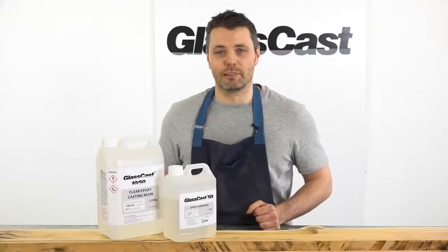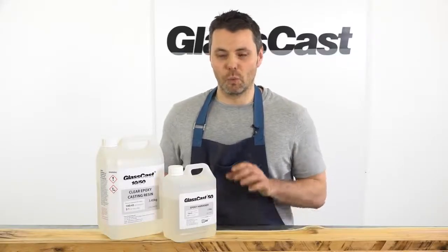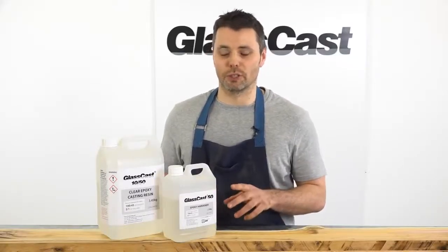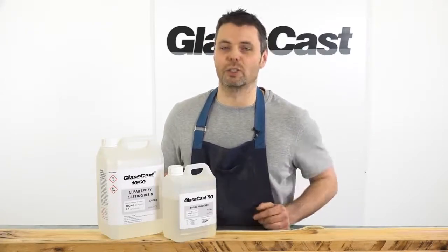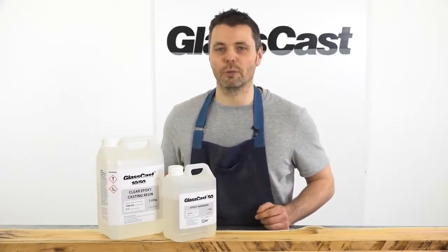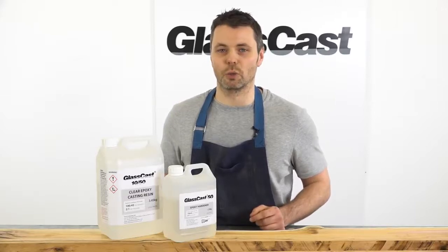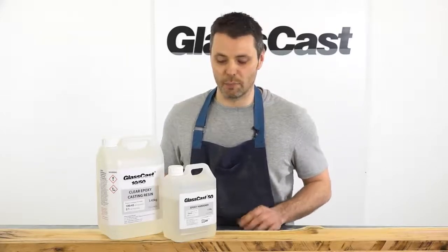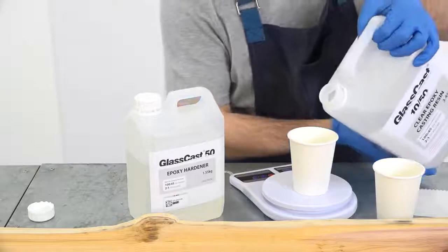Mix ratios vary between the Glass Cast products. With the Glass Cast 50, you've got two options. You can mix by weight, which is 100 parts to 45, or you can mix by volume, and that's at 2:1. Whichever you choose is fine, but just make sure you get that measurement as accurate as possible.